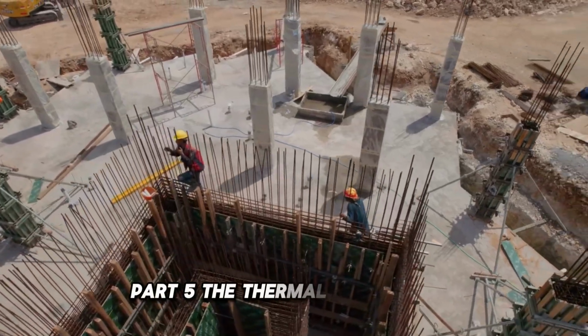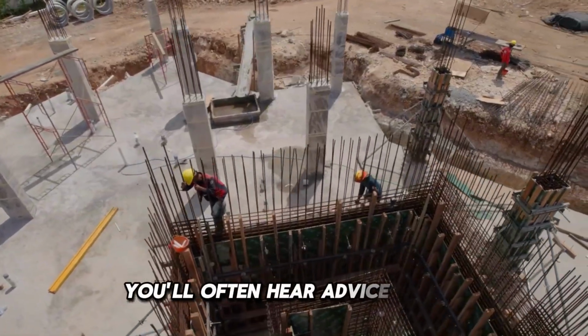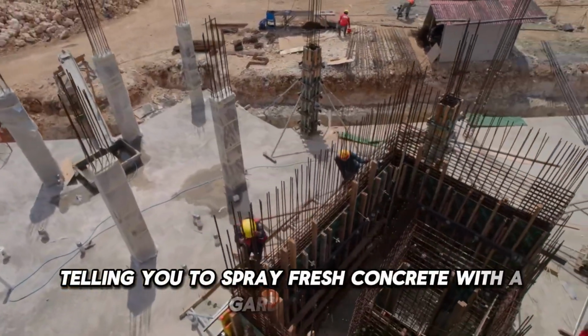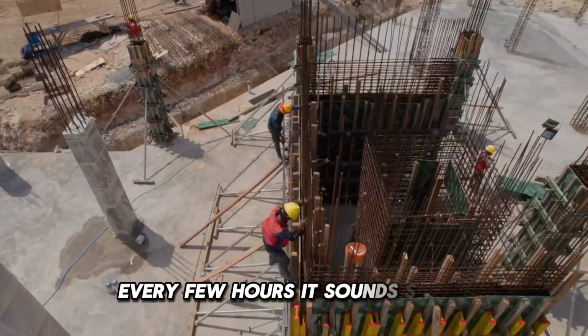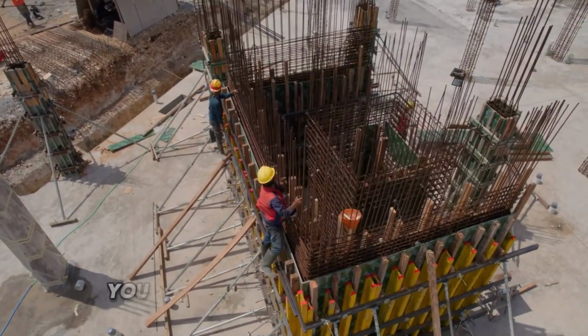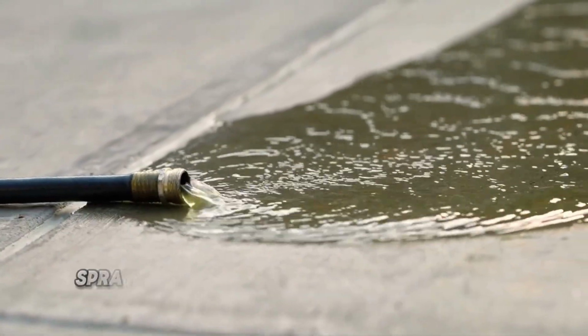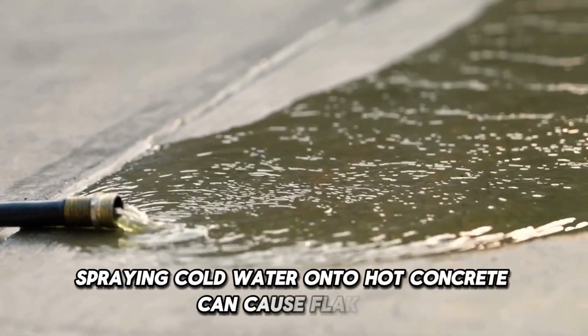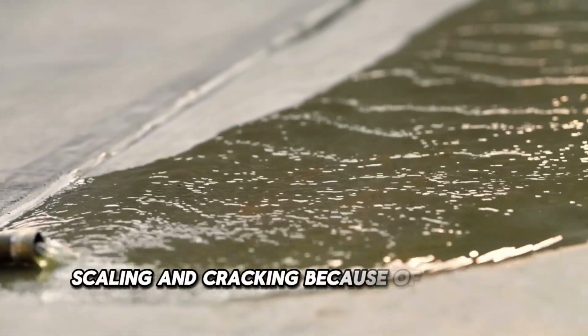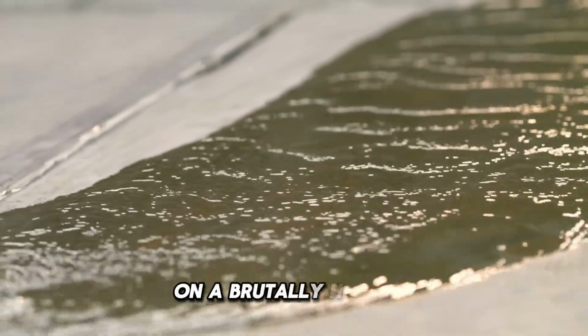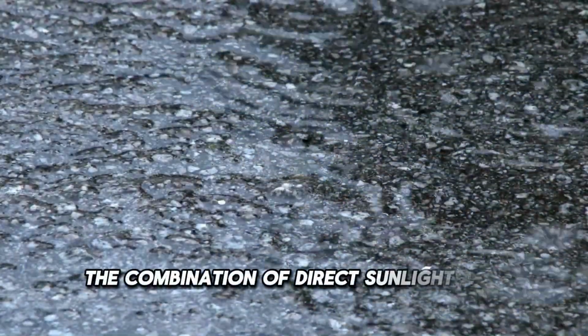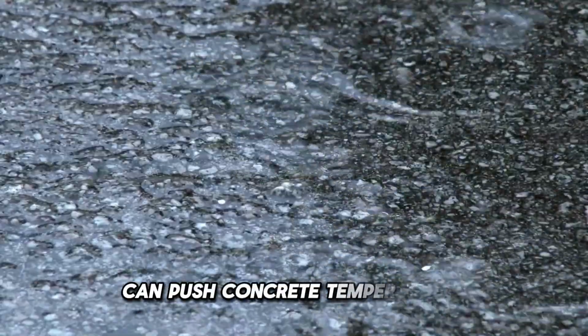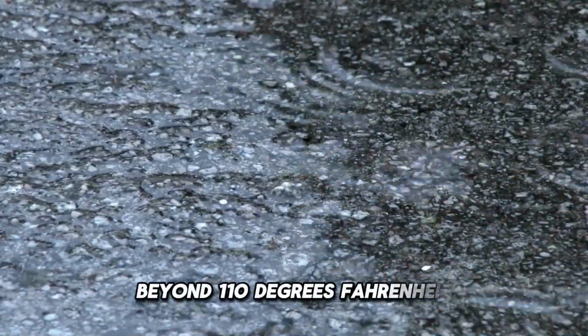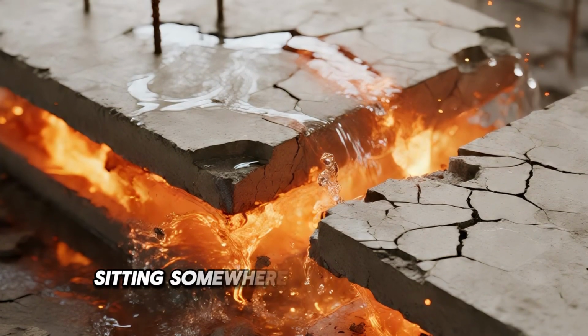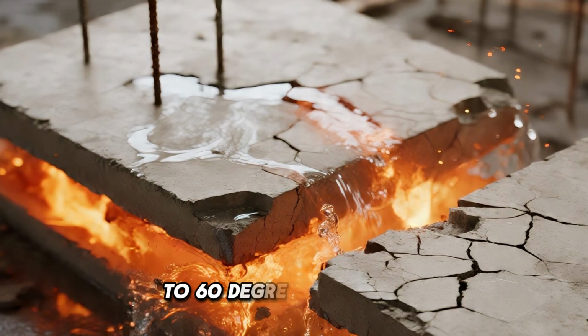Part 5. The Thermal Shock Myth. You'll often hear advice online telling you to spray fresh concrete with a garden hose every few hours. It sounds simple, but if you do it incorrectly, you can seriously damage the slab. Spraying cold water onto hot concrete can cause flaking, scaling, and cracking because of thermal shock. On a brutally hot day, the combination of direct sunlight and hydration heat can push concrete temperatures beyond 110 degrees Fahrenheit. Now imagine suddenly spraying that surface with tap water sitting somewhere around 50 degrees Fahrenheit to 60 degrees Fahrenheit.